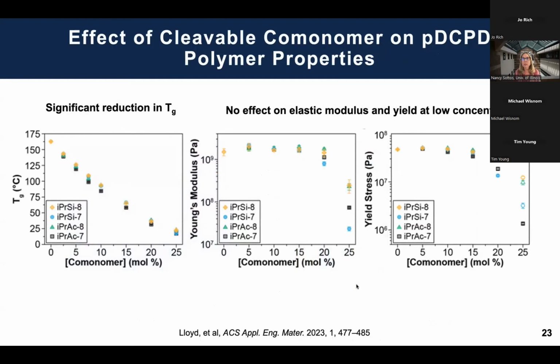The downside of this, though, is that you do take a reduction in some of the network properties of the material. There is a reduction in glass transition temperature because the cleavable comonomer is a big molecule. You see the Tg go down. There's not a big effect at small comonomer concentrations on elastic modulus and yield strength, which is good. So it's mostly this Tg. And so we've chosen to operate in here.